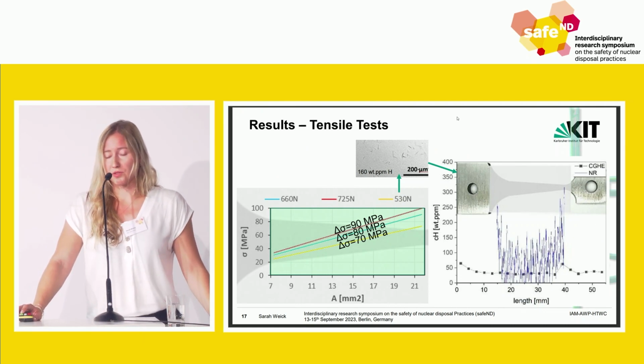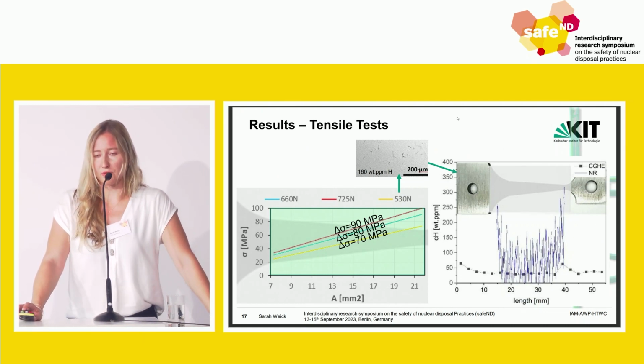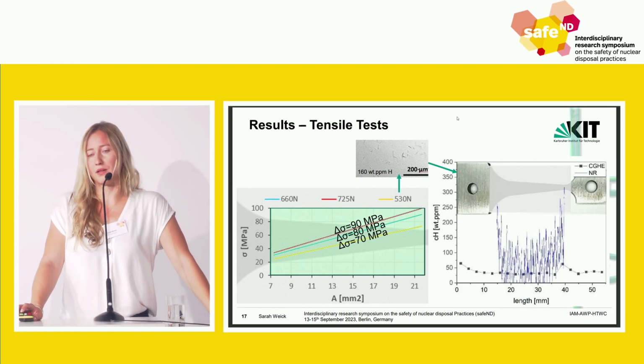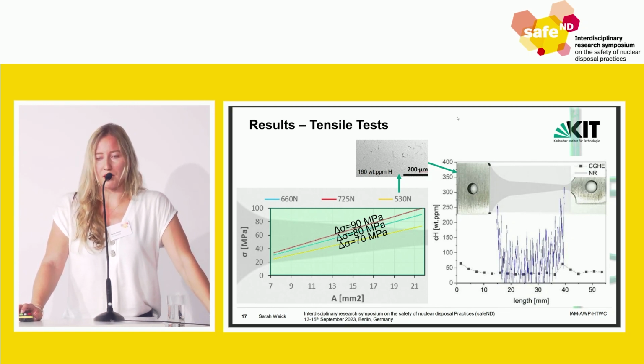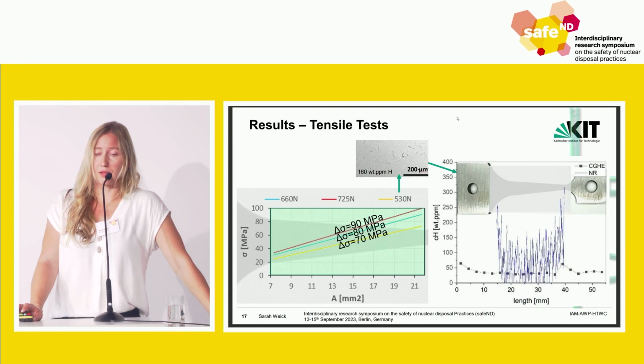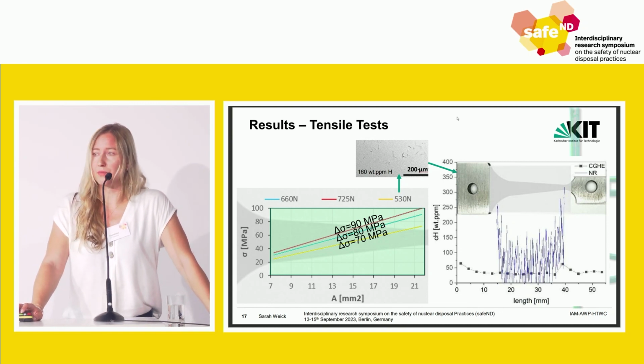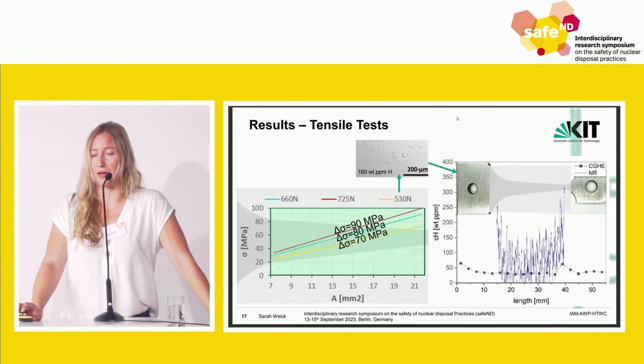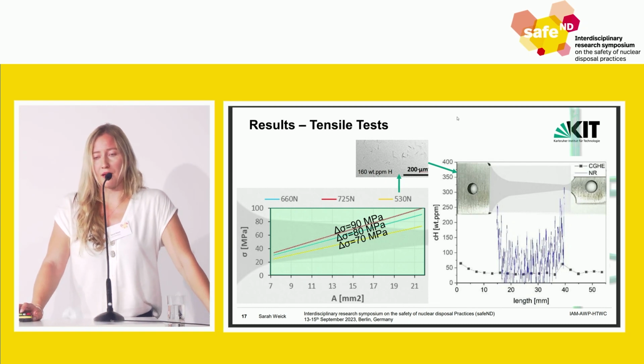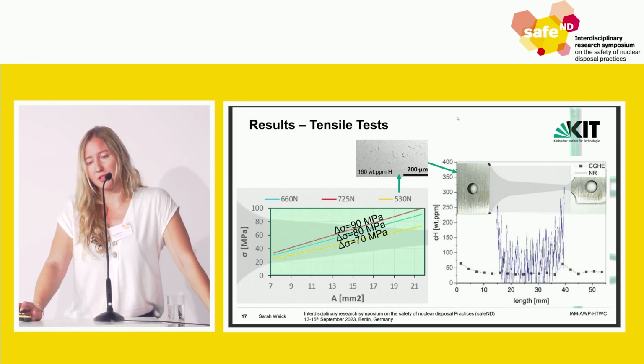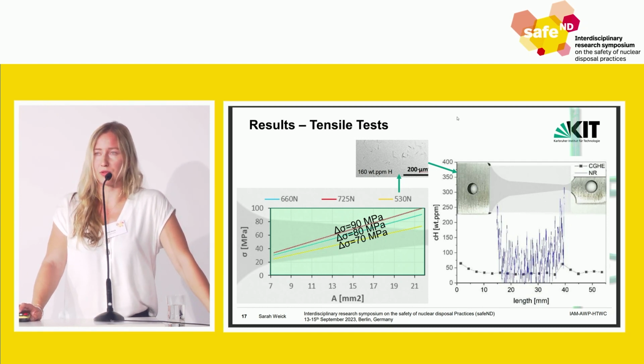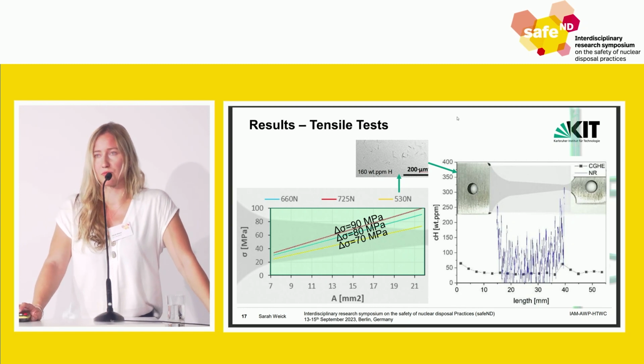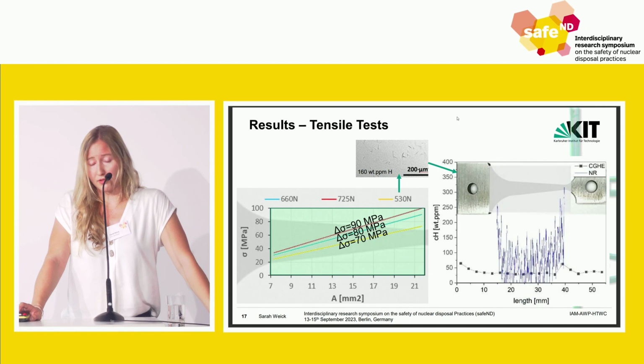And those are some results for the tensile tests we did, for example, with the zirconium tensile samples. You'd expect that, because hydrogen always migrates towards the area with the highest stress, at this point of the region where we have the smallest cross-section of the sample, we would have the highest stress, and then the hydrogen would migrate towards this region. This is what you can see on the right.